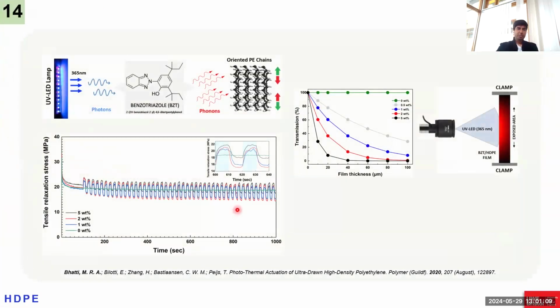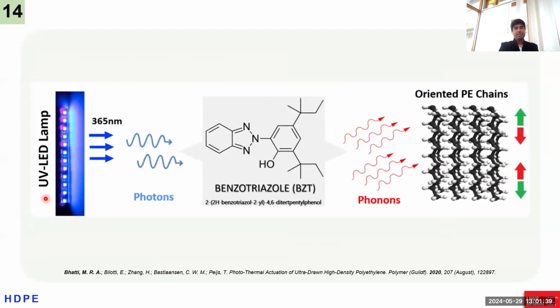So in the following slides, I will talk about some of our research work, starting with the high density polyethylene, because this process is very simple. We can produce high density polyethylene films or filaments or fibers using melt process, which is a very simple process. So we started with creating high density polyethylene embedded with the BZT. We used twin screw extruders to create pellets, and then a single screw extruder to create films. These films contain benzotriazole in different concentrations because we wanted to characterize the different properties of the materials to get the highest possible actuation stress at that time. So what is happening when we illuminate the benzotriazole containing polyethylene films with the UV light?